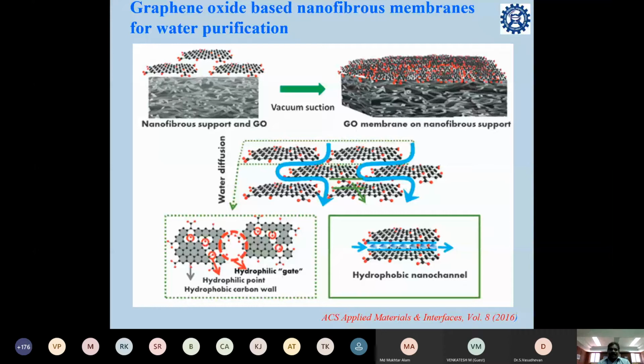So here we can see the water can diffuse through the pores. So this graphene also has pores. Through these pores, that water can be diffused. And if you look at the mechanisms here, there are different types of mechanism that act. Like there are some hydrophilic groups present in graphene, so that will absorb the hydrophilic molecules. And then there are hydrophobic carbon walls present in the graphene that can act as hydrophobic nanochannels to expel the water. So that means both hydrophilic and hydrophobic groups play a vital role in separation of water molecules.